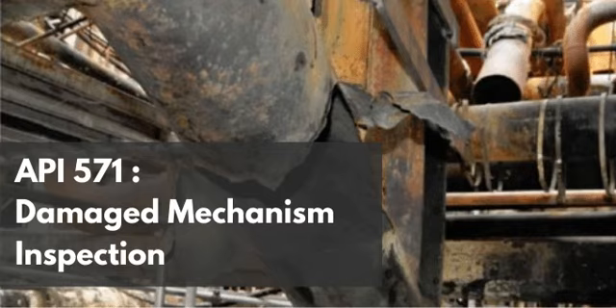All right. Think about the ultimate tragic irony of this mechanism. A massive vessel sits in your unit, operating at 850 degrees for years, and because of the temperature trap, the heat keeps it ductile. Right. It is perfectly stable. But what if the very act of shutting that unit down for a routine mandatory safety inspection, the deliberate act of cooling it down to ambient temperature to make it safe for humans to enter, is the exact thermal trigger that forces the metal across its brittle transition temperature, causing a perfectly stable component to suddenly suffer a catastrophic failure? It gives you chills.